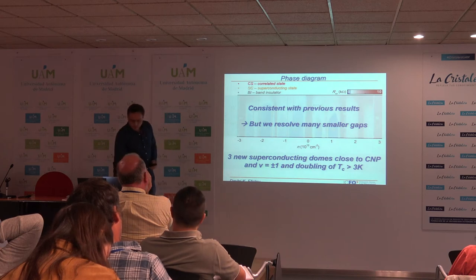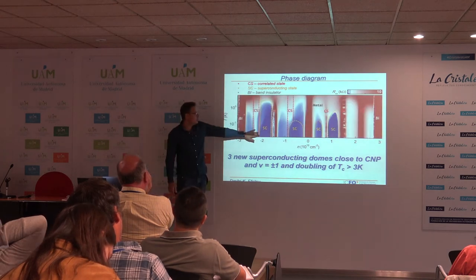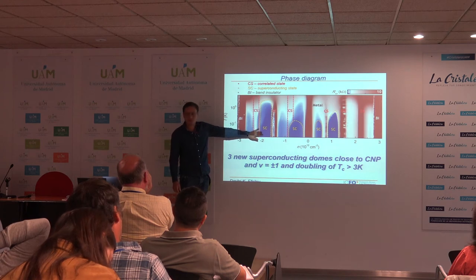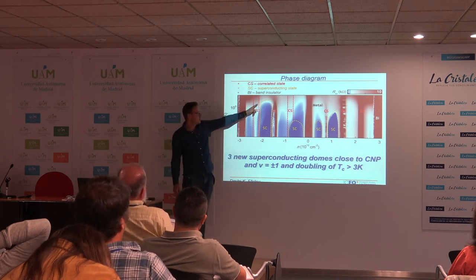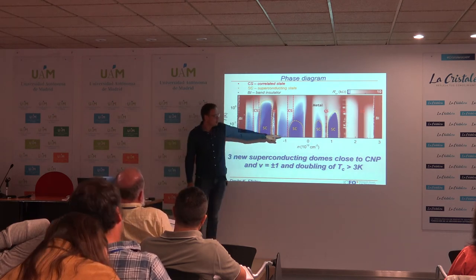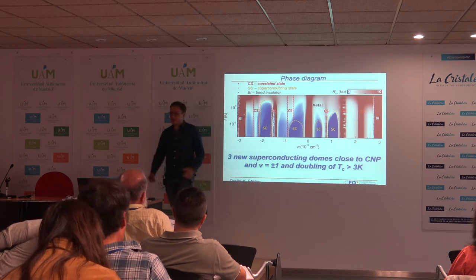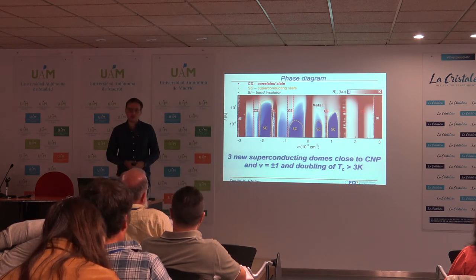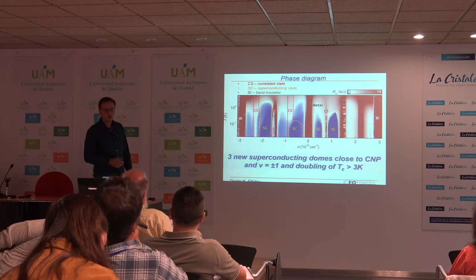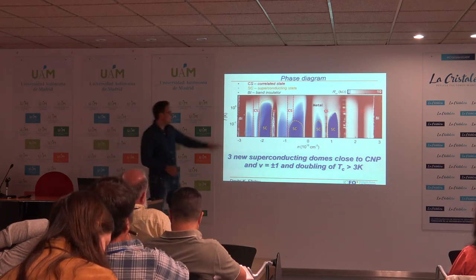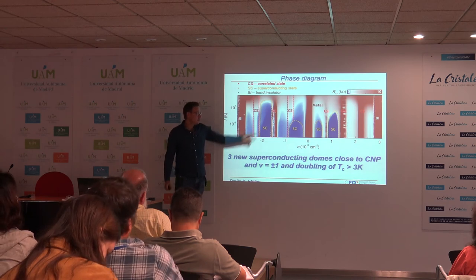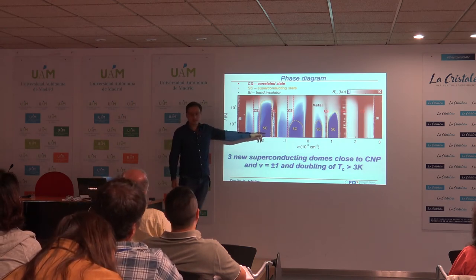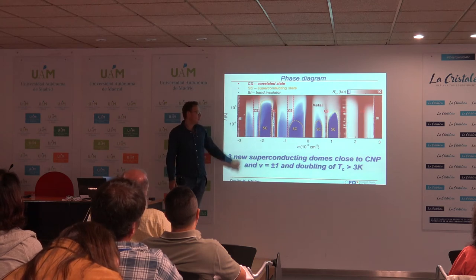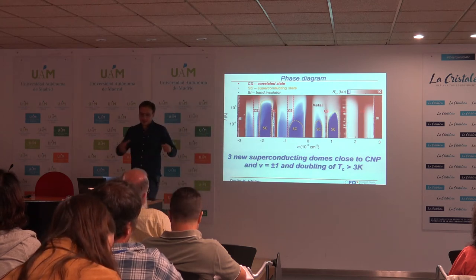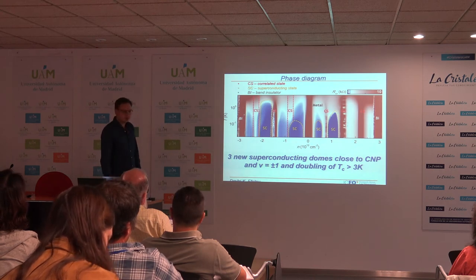And the same is true for the superconductors. So basically, if I look at this superconducting state, which has a TC of 3 Kelvin, this is exactly the same superconducting state which shows the highest TC in Pablo's results. So this is really 3 Kelvin here. However, these other superconducting states have TCs of around 100 millikelvin. So they have TCs which are 30 times smaller than this main superconducting state. So in principle, it is also possible that the origin of these superconducting states is different. For sure, it's possible that such a small superconducting gap could be obscured by a disorder in the system.